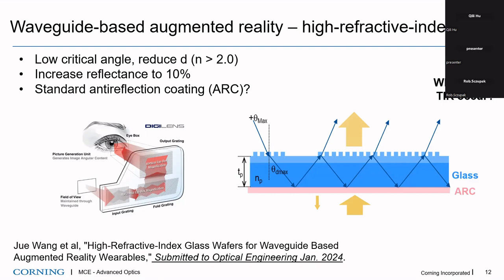This is basically a grating on one side, and on the outermost surface, you put the AR coating. So now the question: can we put a regular broadband AR coating there? It turns out this drawing is actually incorrect, right? Since the total internal reflection actually occurs at the outermost surface, the anti-reflective coating needs to have extremely low absorption. Let's say you have 0.2% at normal view, but in the waveguide mode, the beam is going to bounce around many times. So that requires an extremely low absorption broadband AR coating. So we worked with a facility in China where they make the product, to develop a low loss AR coating for this application.